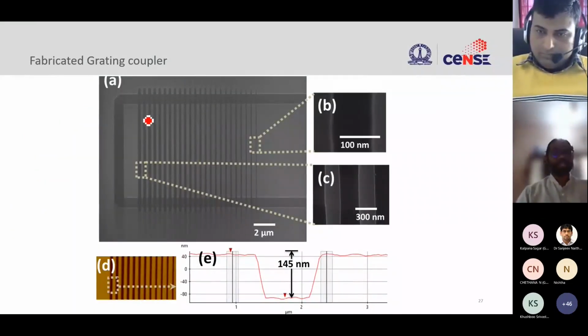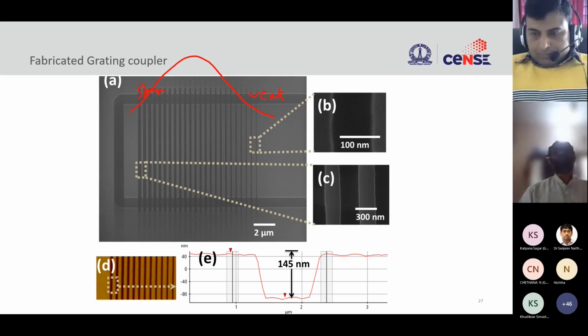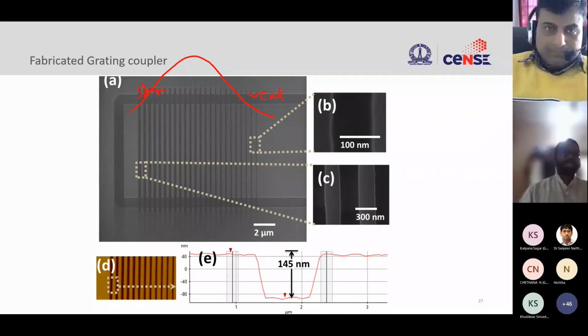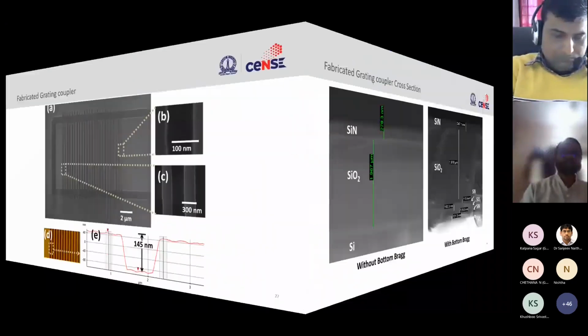So you can see here, this is the apodized grating. You can see here the lines are narrower here and lines are broader here. So this is weak grating and this is a strong grating. So this will result in a diffraction field like this, right? So you can see the AFM image that the edge depth is about 145 nanometers, right? And these are all reasonably small structures. This is about 100 nanometer or so.